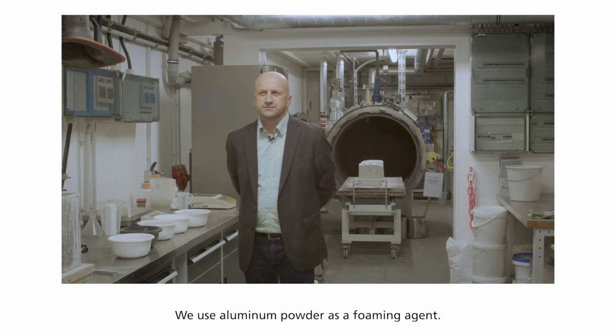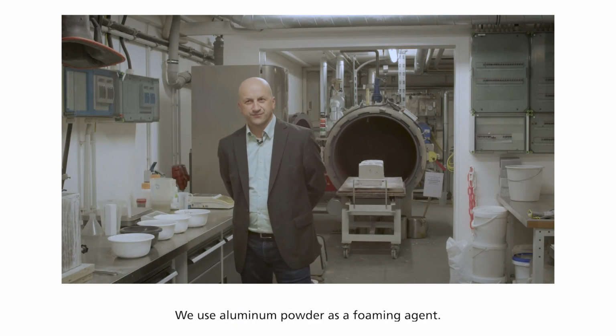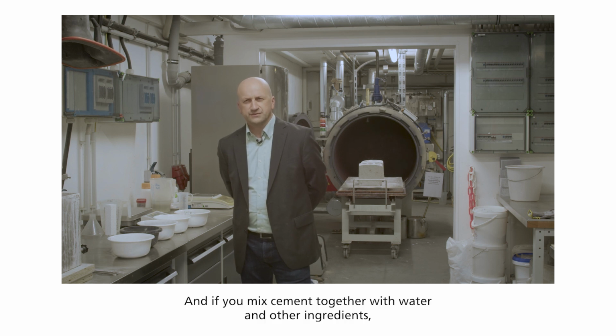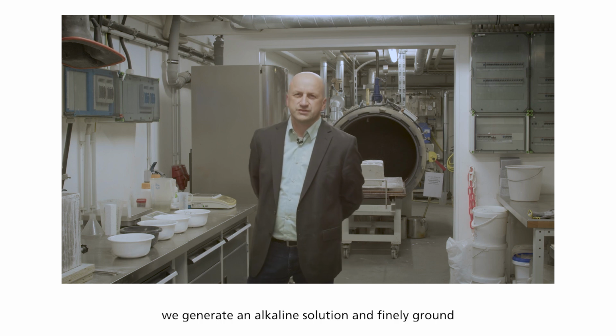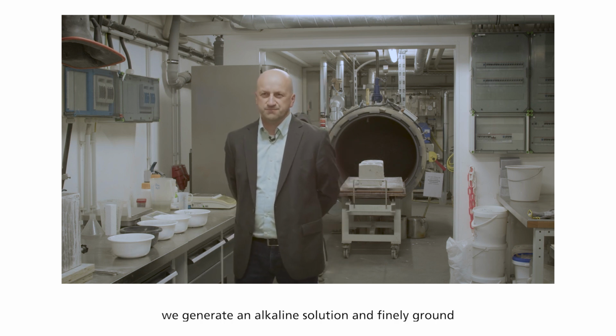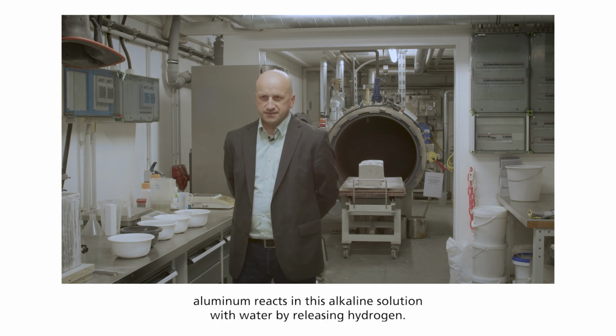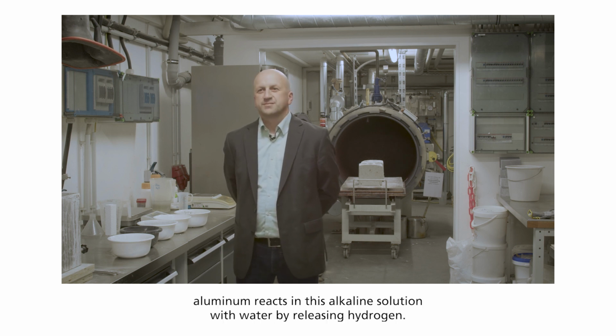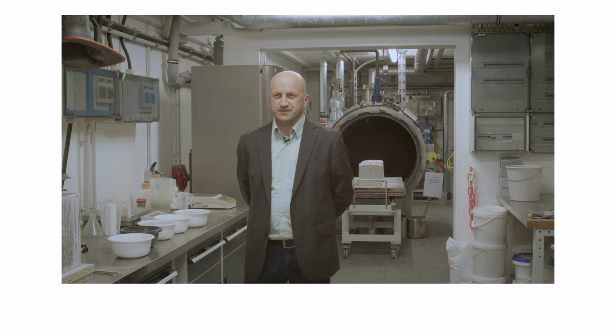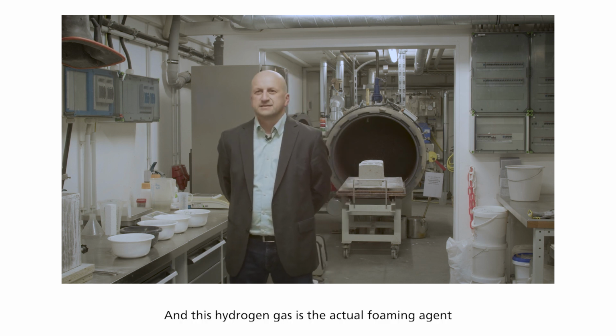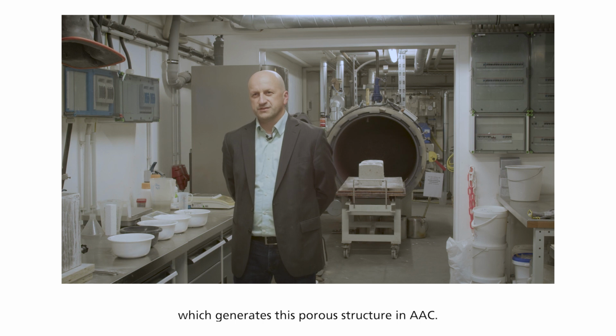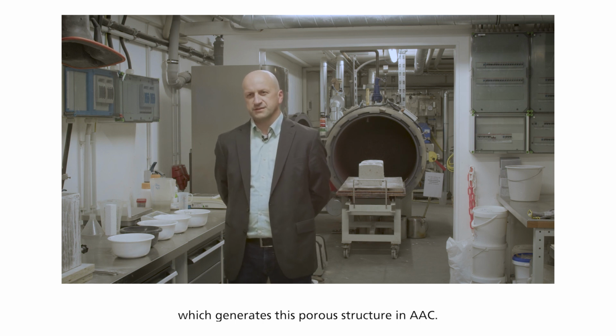We use aluminum powder as a foaming agent, and if you mix cement together with water and the other ingredients, we generate an alkaline solution, and finely ground aluminum reacts in this alkaline solution with water by releasing hydrogen. So this hydrogen gas is the actual foaming agent which generates this porous structure in AAC.